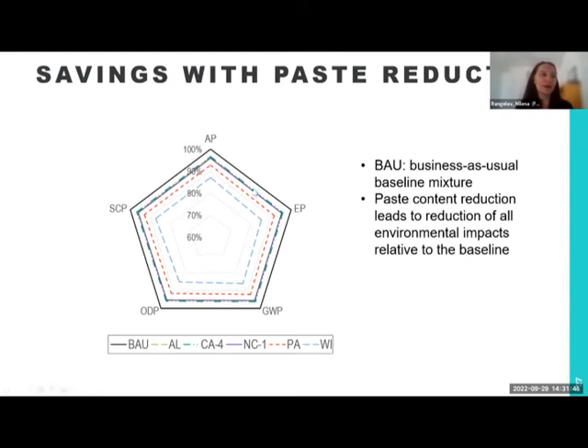In this slide, I'm showing the business as usual baseline mix as the outside pentagon. And then these are improvements in 5 environmental impact categories when we reduce the paste by matching the recommended 25%. And by the way, to do that, you need to optimize your aggregate gradation, which is usually straightforward to do. And we can see here that not only does our GWP improve, and we can achieve up to 16% reduction just by doing that, we also see that all other environmental impact categories are improving at the same time. So we are not having any trade-offs, plus the cost is going to become lower, and durability is going to become less of an issue. So this is a clear win-win situation and is a readily available technology that can be leveraged immediately.